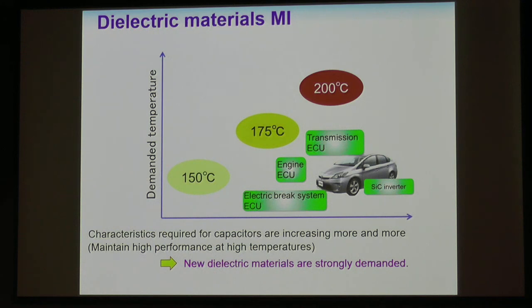So nowadays, multilayer ceramic capacitors are desired to be used at very high temperature. But MLCC materials are mainly composed of ferroelectric barium titanate. In this temperature region, barium titanate goes to the paraelectric phase. This shows a very small dielectric constant. So we cannot use this high temperature region. So paraelectric and high dielectric constant materials are desired.